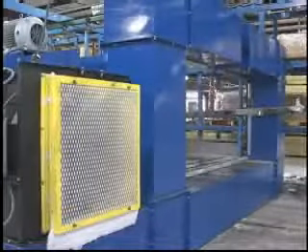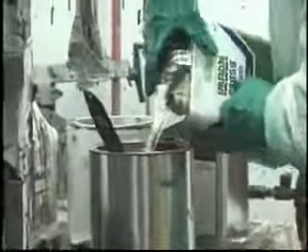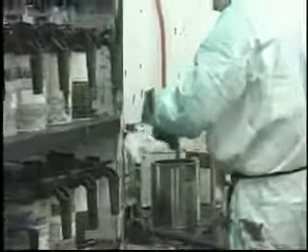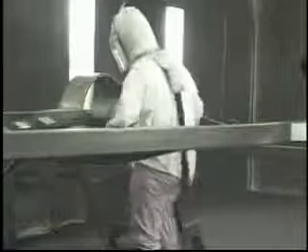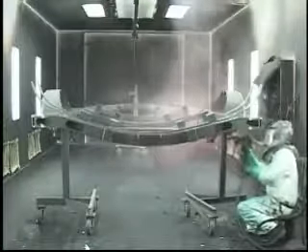Followed by a forced air-drying process. The industrial primer topcoat incorporates a newly developed flexible chip-resistant urethane resin mixture, based on the same chemistry created for Freightliner and Peterbilt truck bumpers. Extensive testing through 500-plus hours of salt spray and humidity have developed a formula that gives the industrial-grade primer greater adhesion with superior rust inhibitors. The finish coat enamel offers our customers a very tough acrylic urethane finish that looks great for years. Colors are custom-mixed on-site, allowing us to match the color scheme of your boats.